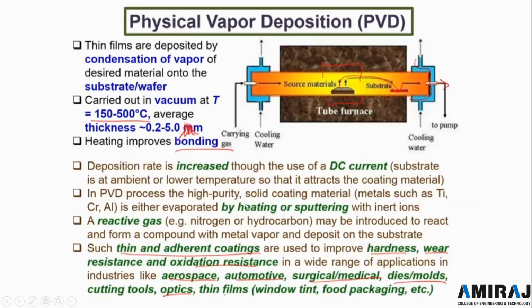In PVD process, the high purity solid coating material, metals such as titanium, chromium, aluminum, is either evaporated by heating or sputtering process with inert ions. Reactive gas, nitrogen, hydrocarbon, may be introduced to react and form a compound with metal vapor and deposit on the substrate. Such thin and adherent coatings are used to improve hardness, wear resistance, and oxidation resistance in a wide range of applications in industries like aerospace, automotive, surgical, medical, dies, molds, cutting tools, optical, thin films, window tint, then food packaging. So these are the various applications of this PVD process.